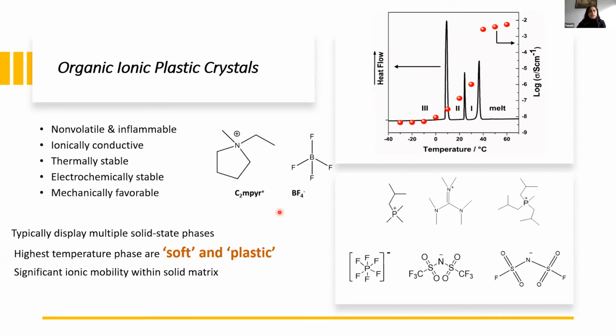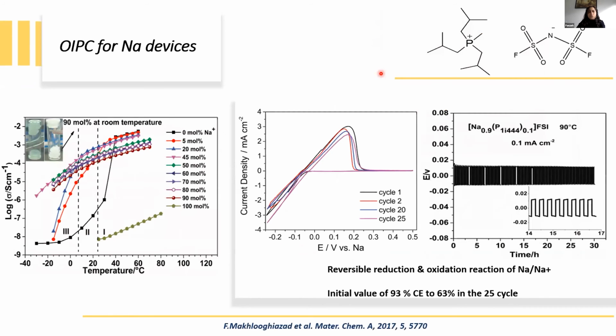So there has been a lot of progress in using plastic crystals with different cations in combination with different anions in our group, in different devices like sodium devices, lithium batteries, and also fuel cells. For example, we have used phosphonium cation plastic crystals with different alkyl chains in combination with different anions for sodium device applications. As an example here, we added a wide range of concentrations of sodium salt into one type of phosphonium cation plastic crystal. And we have shown that the ionic conductivity across the whole concentration range is very high. For example, at 50 degrees, all compositions have ionic conductivity higher than 10 to the power minus 4, which is a high value for solid materials.